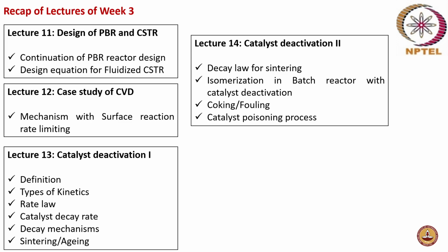So what happens in that case is that the available active sites in the catalyst are reduced. Similarly, it can also happen by narrowing the pore size. Okay, how do the pores get narrowed? It is through blocking. Again, due to long time exposure, especially to the temperatures of the reaction. Okay, in most cases they are high temperature reactions. So these metals tend to melt off and they try to clog the pores. So again here, there is a loss of catalyst.